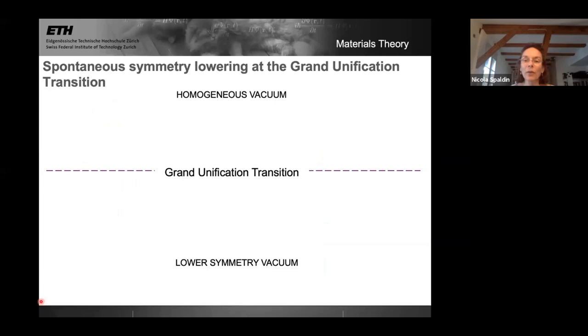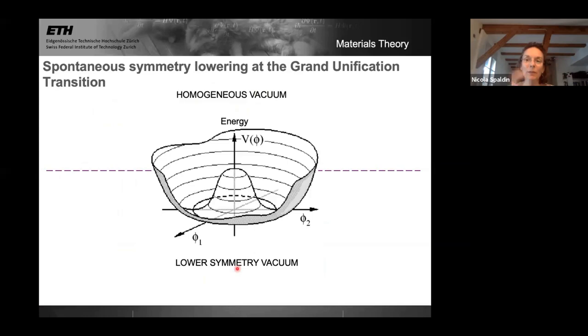Okay, so the grand unification transition is again a spontaneous symmetry lowering phase transition. So it's just like the paramagnetic to ferromagnetic case in a magnet, except this time the system is going from being a vacuum, which is homogeneous, high symmetry, to a vacuum of lower symmetry. And there's one slight technical difference, a slight complication compared with the uniaxial ferromagnet we just looked at. And that's that in this case, the energy surface describing this transition is, rather than just a double well potential, a Mexican hat potential. So it's the familiar form of a Mexican hat potential with high energy at the center of the hat and totally symmetric above the hat, and then cylindrical symmetry in the brim of the hat, and equal energy all the way around the brim of the hat. But still, it's a high symmetry to low symmetry phase transition, this time described by a Mexican hat potential.